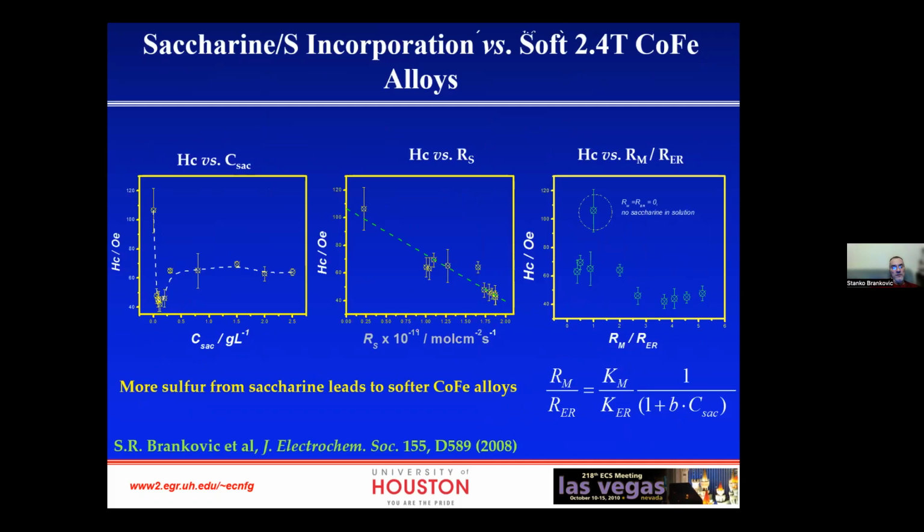So overall, the conclusion of this whole discussion about additives is that we do understand that additives help us with the softer alloys, and we do understand that seeing more molecular incorporation is better than less molecular incorporation, which means we want to design our bath where we maximize molecular incorporation of the additives. And you remember last time we discussed which part is that.